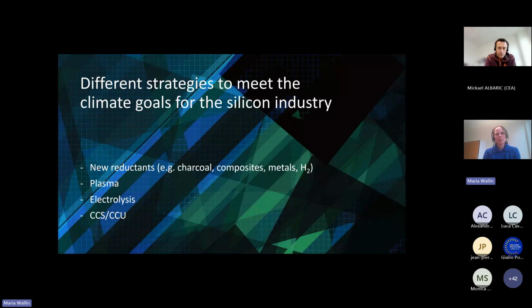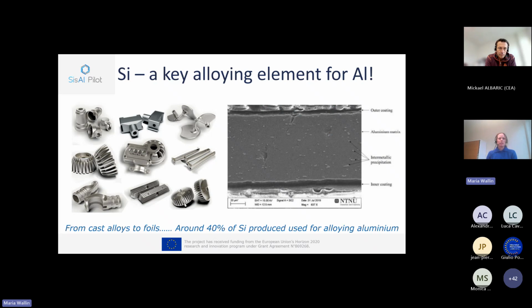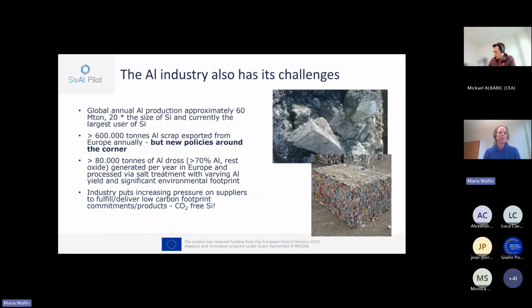And what we looked at in this project is metals. We looked at using aluminium as reductant. And why is that? As I mentioned earlier, roughly 40 to 50% of the silicon produced today is used by the aluminium industry as an alloy element. So why not use it as a reductant to produce a product at the same time? So that's why we looked at aluminium as reductant. And also the reason is that the aluminium industry also has its challenges, because first of all, it's about 20 times larger than the silicon industry. So we produce much more aluminium. And a lot of the aluminium today is shipped out of Europe.